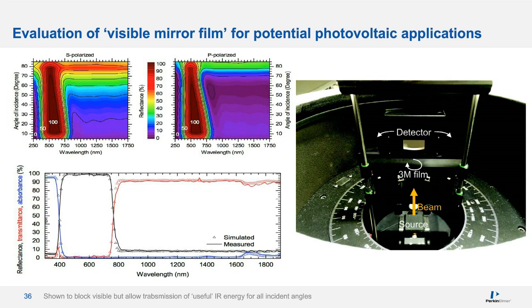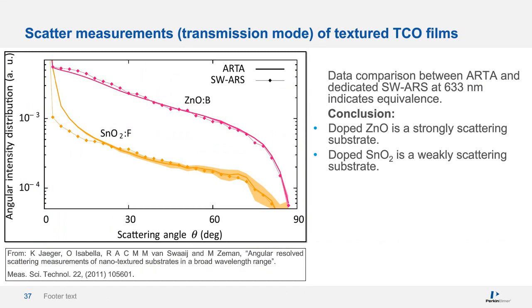The ARTA has also been used to perform scatter measurements, in part to establish its potential in replacing more expensive single wavelength laser-based systems. Such is the case in this slide, where the ARTA was used to characterize the surface preparation of several randomly textured transparent conductive oxides, TCOs. These included doped zinc oxide and doped tin oxide. The data format shown here is angular intensity distribution versus scattering angle. Clearly, the data comparison between the two measurement configurations is very favorable. The ARTA is indeed an appropriate instrument for collecting scattered data.